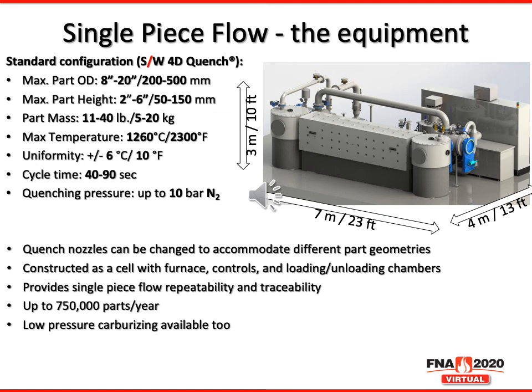What does this mean? It means less downtime, transporting the parts to a different area within the facility or even to a different facility for heat treating. It can all be done in line at once. Also, unlike the batch heat treating process, each part is treated individually, which means each part can be tracked and traced individually and tested individually. That means the results for each part can be certified for each individual part, not each individual lot. And as we mentioned before, case hardening processes like low pressure carburizing can also be handled in this equipment.